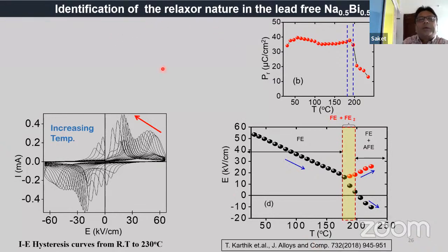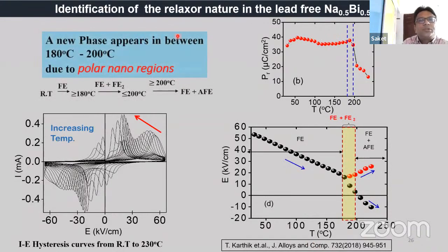Here, on this compound, NBT, there was a lot of ambiguity between 180 to 200 degrees centigrade. People say that it's a ferroelectric phase only. But we have seen that there are two types of ferroelectrics. Earlier it was only ferroelectric from room temperature to 200 degrees centigrade. But we are saying that there are two different types of ferroelectric phases: one will be ferroelectric, another will become antiferroelectric.